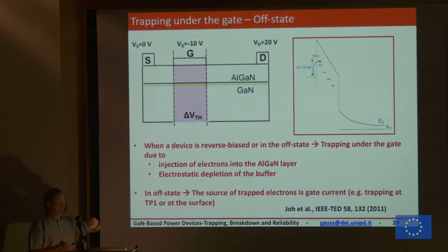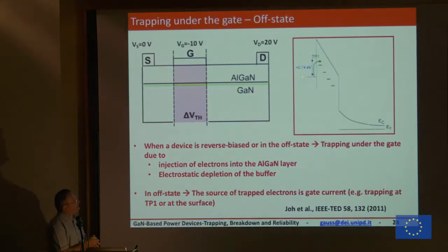So also to give you a little overview, what is related to this current collapse is when we have a negative gate bias. Let me sketch here a very easy band diagram, okay? When I have a very negative gate bias, I push up the metal here. So what we see here is a large electric field, and then the electrons can be injected within the barrier layer to get in towards the buffer. But if we have traps in this area or at the interface here and there, we may have trapped electrons over there. So this is an important point.